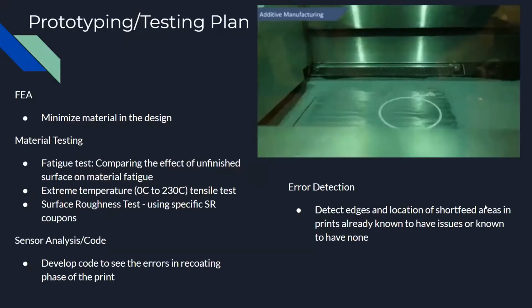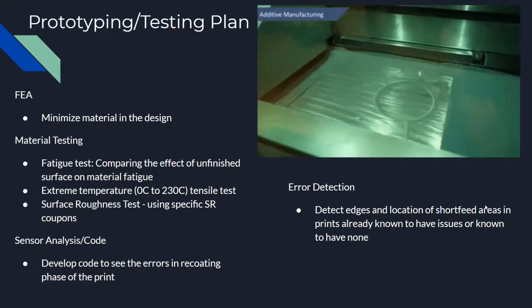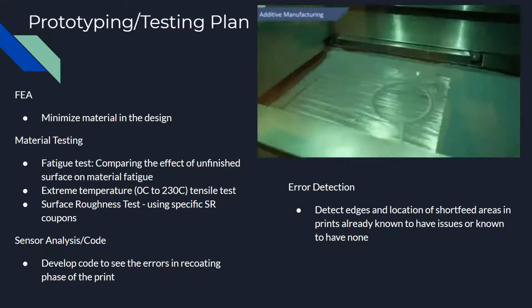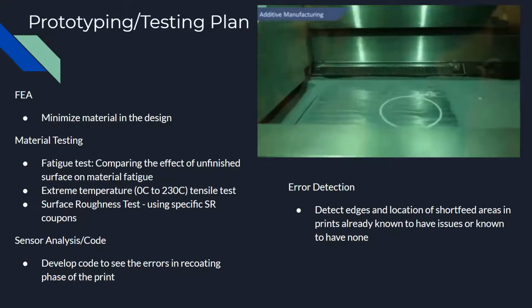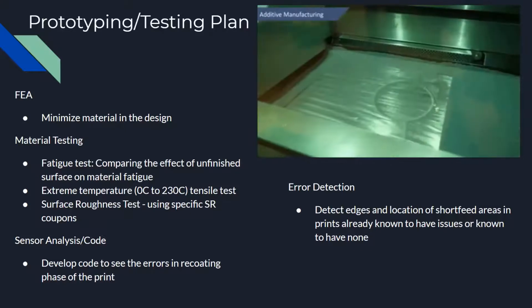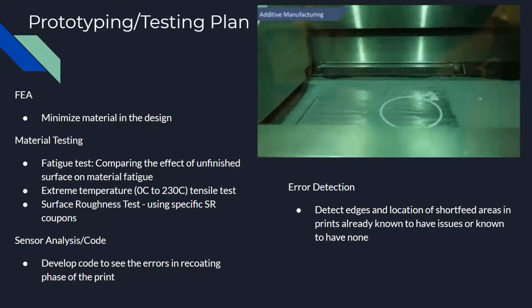For prototyping, we utilized finite element analysis to minimize the amount of material in the design. For testing, we tested fatigue strength of unfinished coupons, tensile strength at high and low temperatures, and surface roughness. We also developed code to detect errors in the recoating phase of the print.